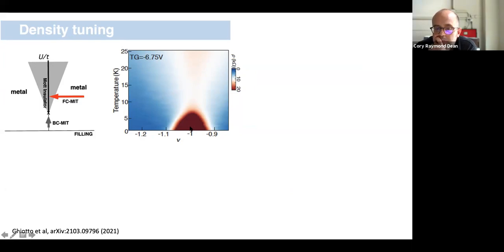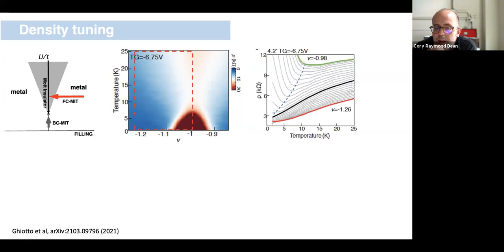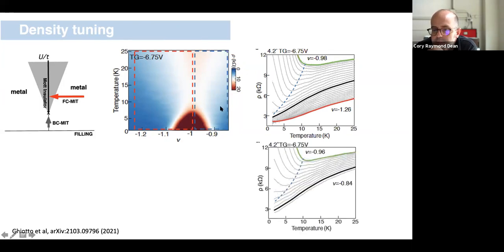And what I want to do now is look at what happens if I'm on the positive doping side of this Mott gap. And here we're just plotting R versus T line cuts. What we see is that indeed, as I move from the insulator to higher doping, we transition from an insulating-like state to a purely metallic state. And if I dope in the negative sense, so fewer holes, if I underdope relative to this dome, same thing, we transition from an insulating state to a metallic-like state.